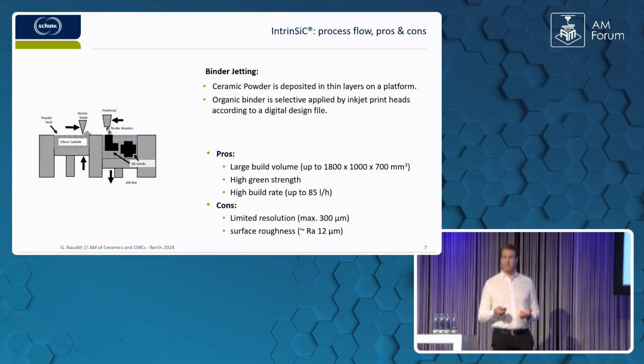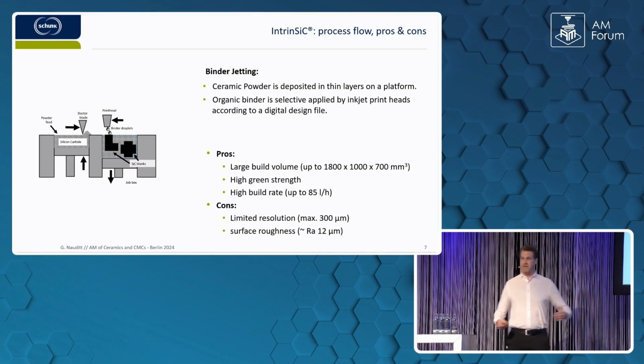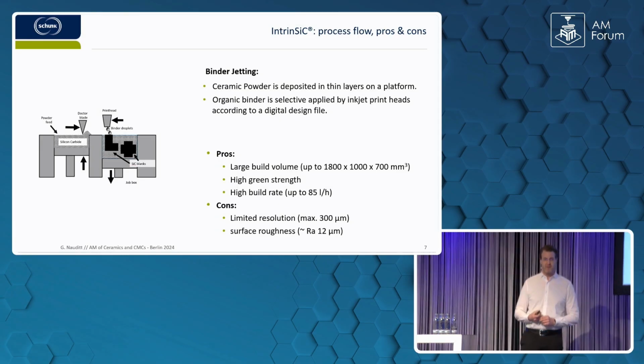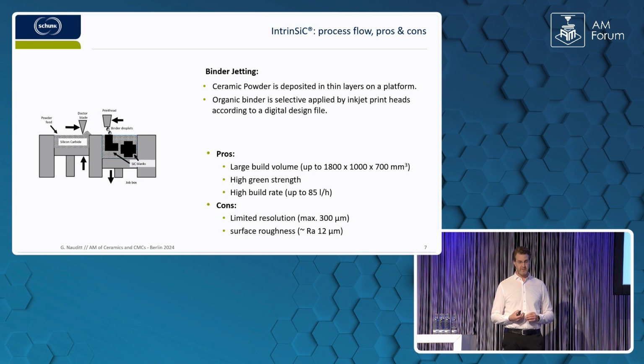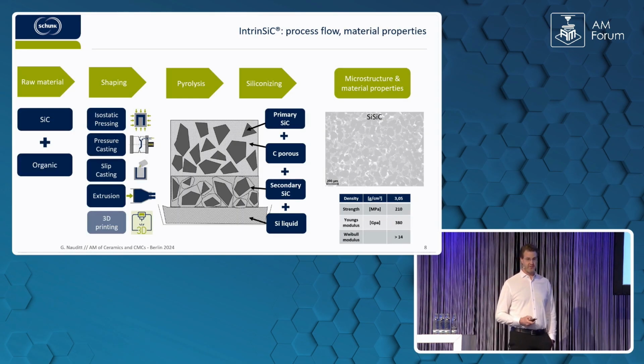The beauty of the powder bed process is you can scale it really easily. We can have big dimensions, and right now we are able to print 1.8 by 1 meter in footprint and build area, and we can print 85 liters per hour, which is quite fast. So it gives us a high flexibility and a good print rate. Of course, we have a limited resolution of 300 microns because of the powder, which gives a rougher surface.